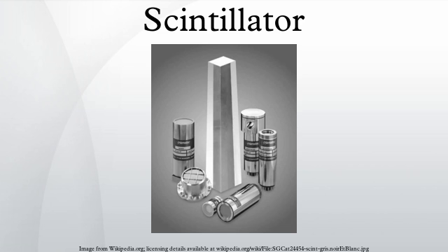Organic liquids: these are liquid solutions of one or more organic scintillators in an organic solvent. The typical solutes are fluors such as p-terphenyl, PBD, butyl-PBD, PPO, and wavelength shifters such as POPOP. The most widely used solvents are toluene, xylene, benzene, phenylcyclohexane, triethylbenzene, and decalin.